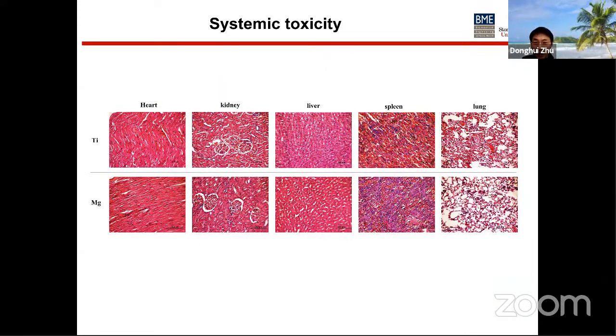Lastly, we checked systemic toxicity by looking at histological analysis of different internal organs. No sign of systemic toxicity was found. The hemolysis and lipemia index of the blood are normal, and the chemistry panel from blood analysis shows no significant difference between groups, all within the normal range of these parameters. Systemic toxicity appeared to be not a concern.